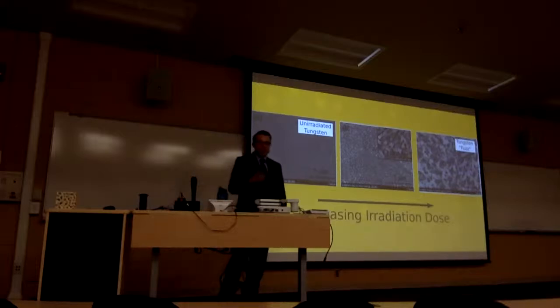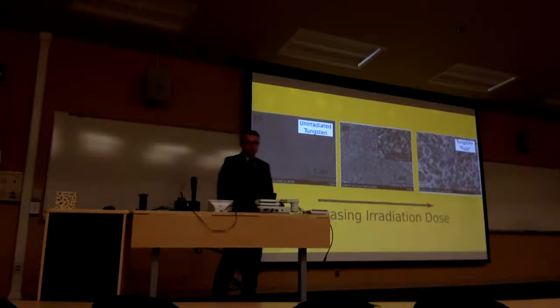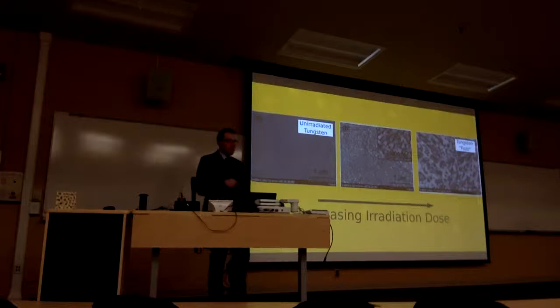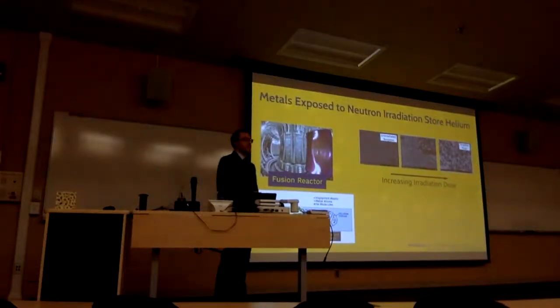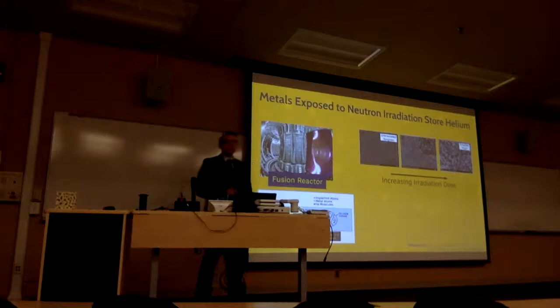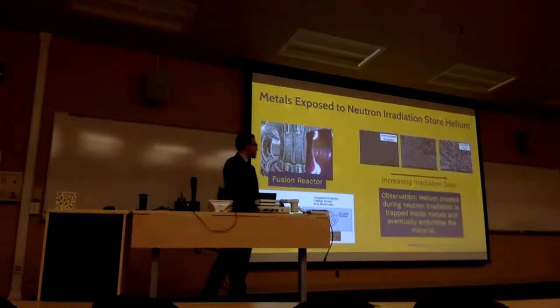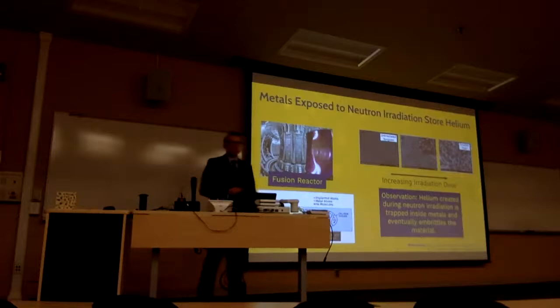So take this fully dense tungsten sample here. As we hit it with neutron irradiation, the sample actually develops pores throughout the tungsten material. And we dub this tungsten fuzz because it develops into this porous-like structure. The structure embrittles at high irradiation dose, and that becomes a problem if we're using these types of materials in a fusion reactor or nuclear application. So we observe this helium that gets trapped inside of the metal and eventually embrittles the material and it fails.